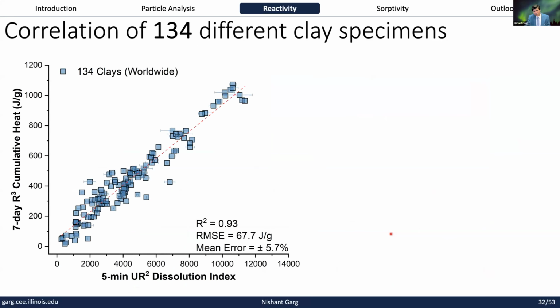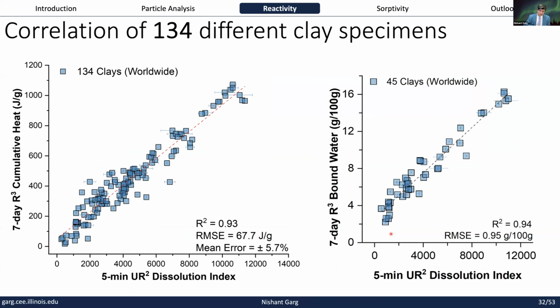And we have now done this test on almost 130 unique clay specimens. In the paper that came out earlier this year, we had data on 50 clay specimens, and since then we have done 80 more. Once we developed that master curve, it started to become quite general, and those 80 additional samples basically lie on the original master curve. If we compare a subset of this data with the bound water, we also get a very decent correlation. So we are very excited by these results, that now in 5 minutes you can predict the reactivity of these clays.